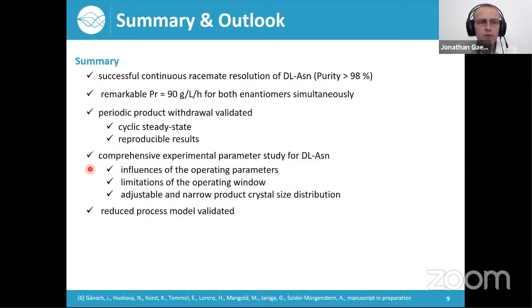Then I showed you some results of a comprehensive experimental parameter study, which was directed to study the influences of the operating parameters, but where we also could find some limitations of the operating window and we could prove this adjustable and narrow product crystal size distribution. And I showed you that there has already been a reduced process model developed, which has a very good quantitative agreement with our experimental results.